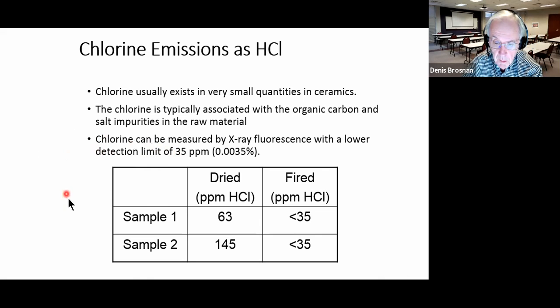So in a couple of samples I looked at that were natural materials containing natural carbon, you can see that there was a little difference here in the chlorine content defined as HCl, and once it's fired, that contains less than that determined by X-ray fluorescence.